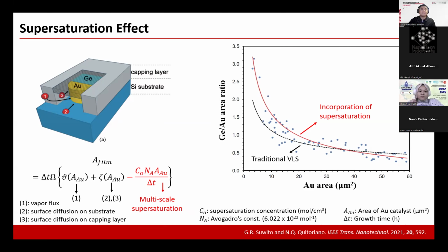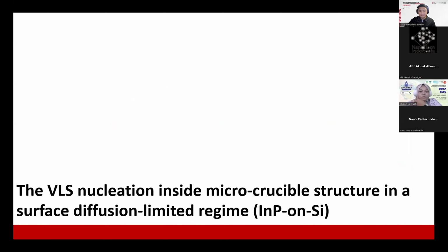So we've been able to reconcile the nanoscale and microscale VLS process using this supersaturation term. Okay, so now let's discuss the results we have for indium phosphide on silicon. This is a bit different because it was grown in what's called a surface diffusion limited regime by chemical beam epitaxy, or CBE, which is different from the previous ones, which were grown in a CVD chamber.